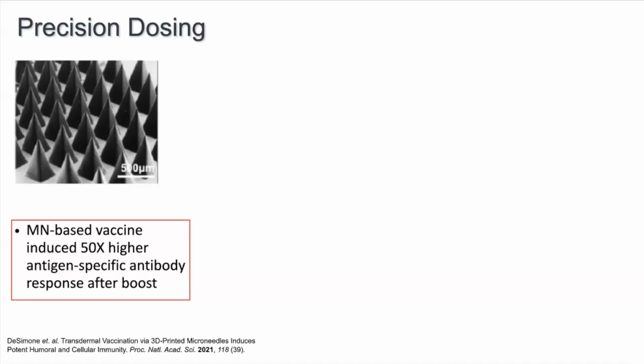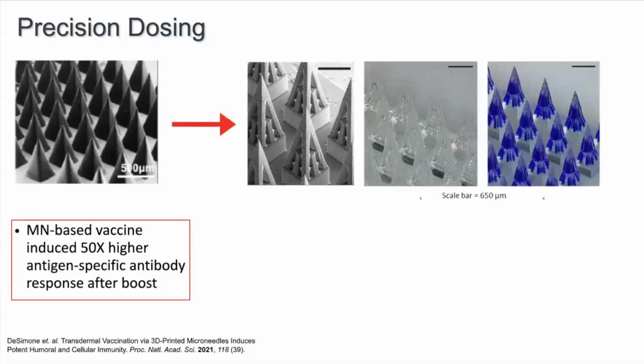But what we found is you can deliver the same amount of vaccine into the dermis, and you can get a 50-fold increase in antibody response. There's a huge dose sparing. You don't have to deliver as much vaccine to have a really strong response.